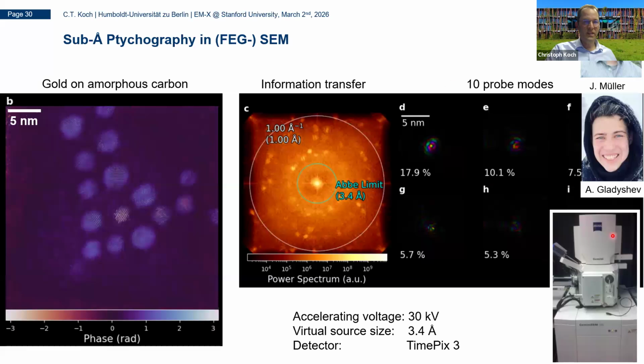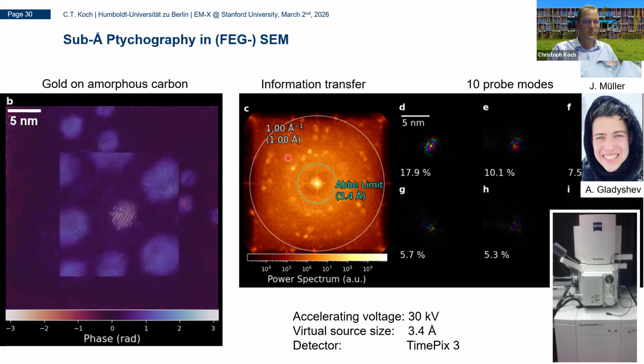And now this simple SEM that I've shown you, the microscope that we have in our lab, where we put a Timepix detector in. Unfortunately, we didn't record the information out to very high scattering angles, and have not really used multi-slice ptychography yet, but even this is the range of the detected scattering angles, and really the resolution goes all the way out to where we've recorded information. So we should repeat the experiment now. This is a very recent experiment, but we should repeat it now really with larger scattering angles and see how far the resolution can go. Interestingly, in contrast to this microscope I showed on the previous slide, which had a cold field emission source, this has a regular field emission source. And so the virtual source size was 3.4 angstroms, yet the resolution we extracted was less than 1 angstrom, actually.